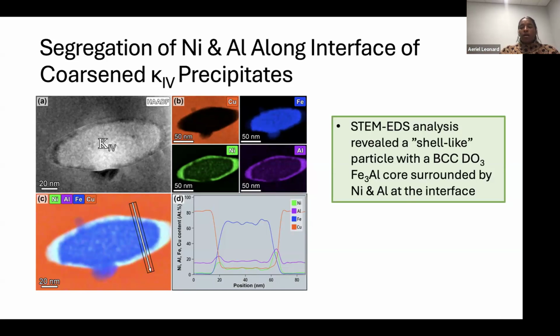And so in the wire arc processing procedure, if we're printing 10 bars, the first layer of each bar is printed, and then the second layer of each bar is printed. Because we're holding the chamber at 350 degrees Celsius until the last layer is printed for every bar, it's pretty much getting a heat treatment as the printing process is progressing. And so basically what we were seeing was the coarsening of kappa 4 and the segregation of nickel and aluminum along the interface.